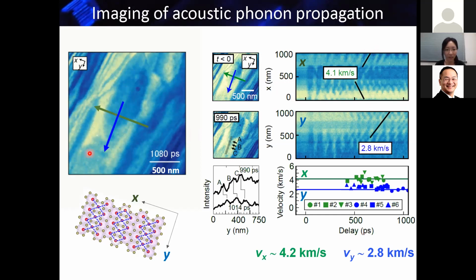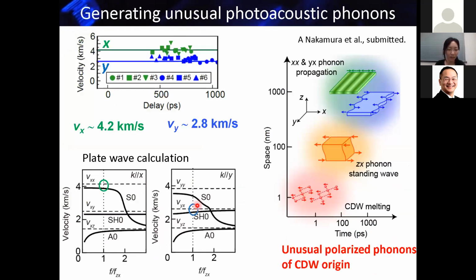For the y direction, we do a similar thing, and then we can also estimate the sound velocity along the y direction. And we find that there is a significant difference between the x direction and the y direction. Along x, the sound velocity was around 4 kilometers per second, but along y it's like 2.8, which is quite different. I won't go into the detail, but by doing a sound wave calculation inside this thin plate, we find a nice agreement. What we can conclude from this is that the phonon dynamics or strain dynamics in this material is very unusual, or irregular.